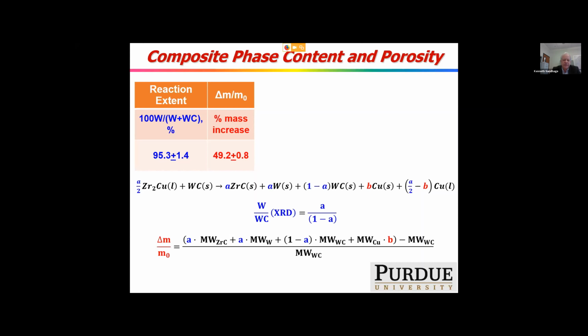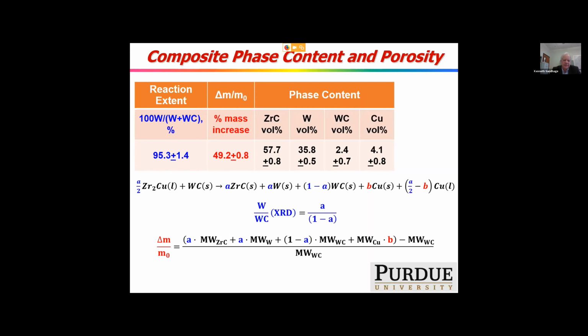If we can determine those two parameters in that reaction, A and B, we can unambiguously determine the phase content. A, we get from quantitative X-ray diffraction analysis by looking at the tungsten to tungsten carbide ratio, as I mentioned. If we measure the mass change, we know from the reaction what contributes to the mass change. We can determine B, and from those two parameters, we can determine unambiguously the phase content, which is typically around 58 volume percent ZrC, about 36 volume percent tungsten. They're both interconnected phases, and smaller amounts of residual tungsten carbide and copper.